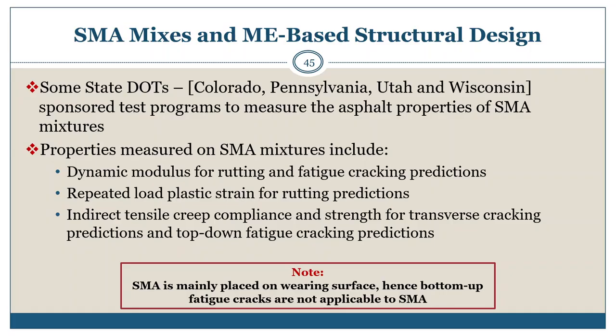In support of the use of mechanistic empirical based methods, some state Departments of Transportation, for example Colorado, Pennsylvania, Utah, and Wisconsin, have sponsored test programs to measure the asphalt properties of SMA mixtures. Properties measured on SMA mixtures include dynamic modulus, for predicting rutting and fatigue cracking, repeated load plastic strain for predicting rutting, indirect tensile creep compliance and strength for predicting low temperature or transverse cracking, and also top-down fatigue cracking.